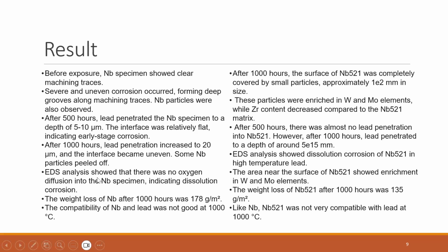EDS analysis shows there was no oxygen diffusion into the niobium specimen, indicating dissolution corrosion. The weight loss of niobium after 1000 hours was 178 gram per meter squared. The compatibility of niobium and lead was not good at